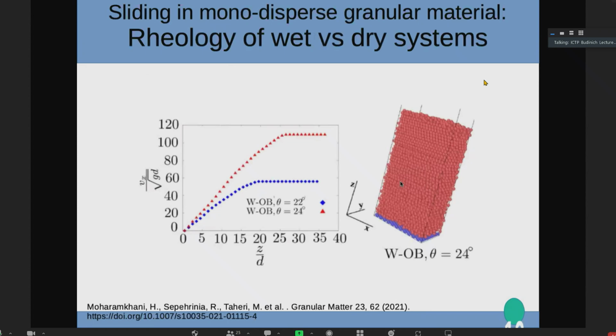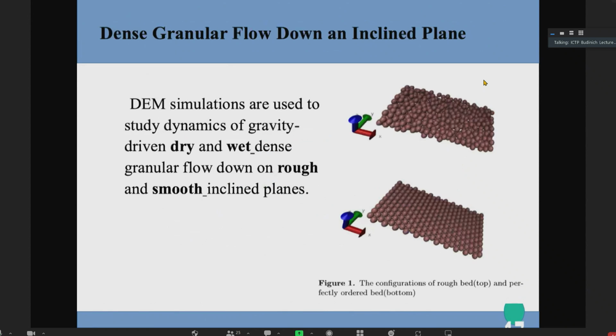Here you see that if we have a smooth substrate and we add a little moisture in a given granular system, it is possible to have at first a shear band at the top of the system, which means that the velocity profile at the top of the system is completely the same, and the rest is almost a monotonic increase in velocity profile of the system. What made us more interested in this problem was the ordering-disordering transition during the rheology, in the dynamics of the system.